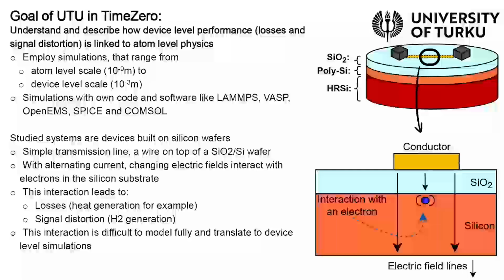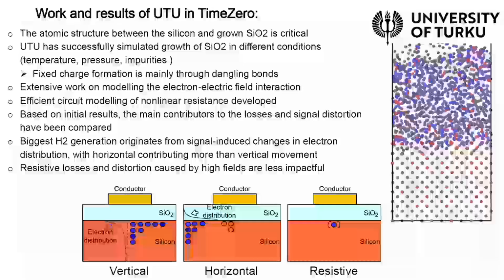It's a challenging path from the atomic scale to the device scale, but there's significant progress. So first of all, the silicon oxidization has been modeled by Turku, in different conditions, and it's been found out that the charge formation is mainly from the dangling bonds, and extensive work has been done on the electron electric field interaction there. It's a very computationally heavy simulation, so an efficient circuit model for this behavior has been developed.